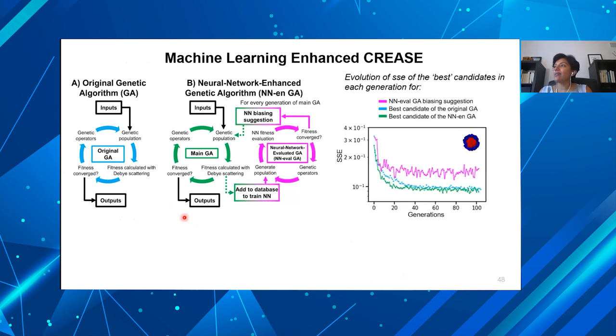And so this was work, last chapter of one of my other students' thesis. What we found is that compared to the original genetic algorithm, which is in blue, this is the sum of squared errors. The lower this is, the fitness is high, and the faster it converges, fitness converges fast, we get an answer fast. So you notice that the blue has this behavior over generations. This new cycle is similar to the original with the difference that every generation we train a neural network model and use that to quickly calculate I_comp, suggest a candidate, send it back to the main. So the main is still slow, but this side is very fast.